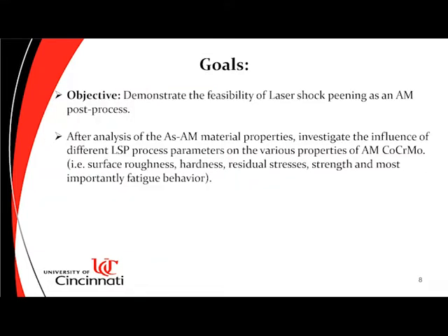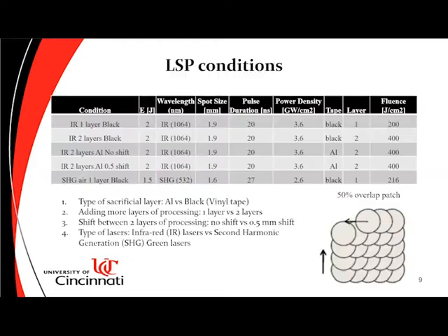So the main goal of this project is to demonstrate the feasibility of LSP as an AM post-process technique, and also investigate the influence of different LSP process parameters on the various properties of the additive manufactured cobalt-chromium alloy. For this experiment, a few LSP parameters were varied to understand their impact on enhancing the investigated properties. The different conditions used are presented in this table. There are 5 conditions we use. For 4 conditions we use the infrared laser, for 1 we use the green laser. Out of the 4, for 2 conditions we use black tape, and for 2 we use aluminum tape.